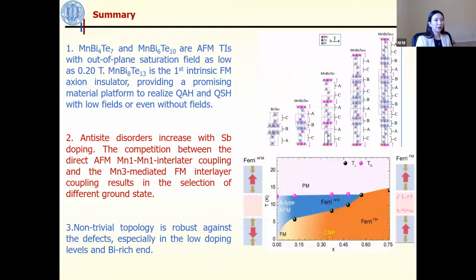So here is the summary of the talk. Hopefully, I have given you an overall picture about the so-called manganese 1, bismuth 2n, tellurium 3n plus 1 family, right? So MnBi4Te7 and MnBi6Te10 are antiferromagnetic topological insulators. 1813 is the first intrinsic ferromagnetic axion insulator. And they provide a promising material platform to realize QAH and QSH with low fields or even without fields.